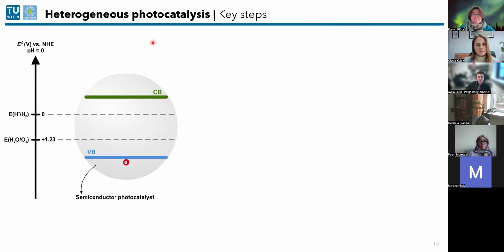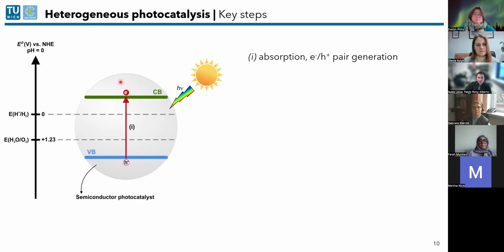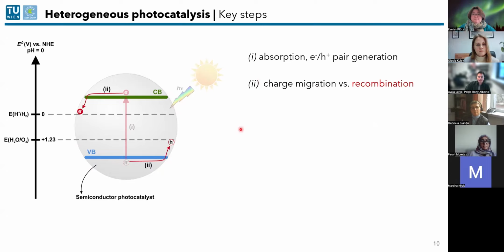So in heterogeneous photocatalysis, we have 3 key steps. So we have our semiconductor photoabsorber, which has a valence band and a conduction band, as you may know. And when we illuminate with light, we generate an electron-hole pair, or excitons, or charge carriers, through light absorption. This is step one. Then in step two, these charge carriers have to travel to the surface. So we have charge migration. The opposite process here being recombination.